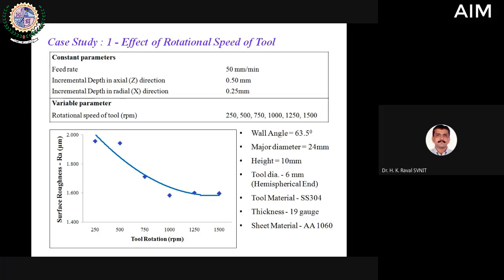We tried six different tool rotation RPMs, keeping other parameters constant, and the surface roughness was obtained. It was found that the surface roughness was minimum, around 1.6 micron, at a tool RPM of around 1250 or 1500. So that was one point where we could reach the conclusion that the higher the RPM, the better the surface finish that can be achieved. But still we did further trials. This result was for one angle of 63 degrees.